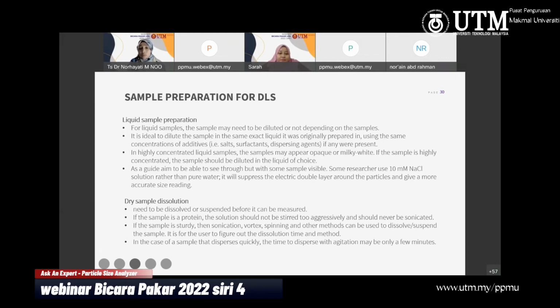In highly concentrated liquid samples, the samples may appear opaque or milky white. If the sample is highly concentrated, like opaque fresh milk, then it should be diluted a little bit, so that the laser can go into the sample and scatter off the particles. If it is too concentrated, the particles move slowly and it could give you multiple scattering, which might give you the wrong result. You still get a result, but it is wrong.